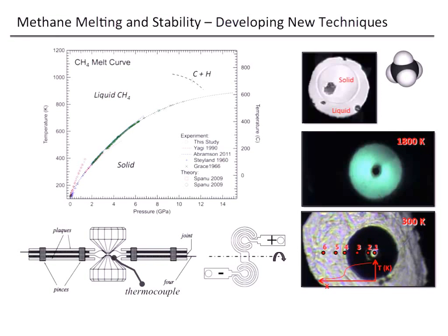So one of the things we're working on is developing techniques to put couplers that are chemically inert in the sample. What you see here is the edge of the gasket, and this reticulated pattern is solid methane, and this is a boron-doped diamond little donut that we make with a focused ion beam. The idea is that we contain the hot methane within the center of the donut here.